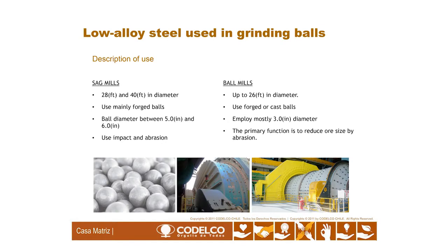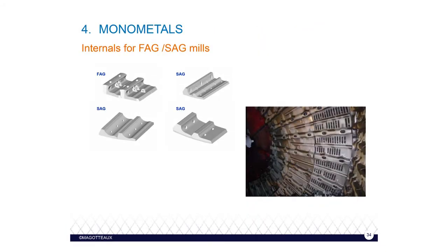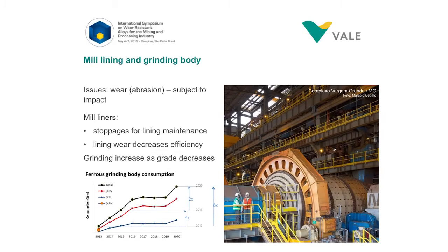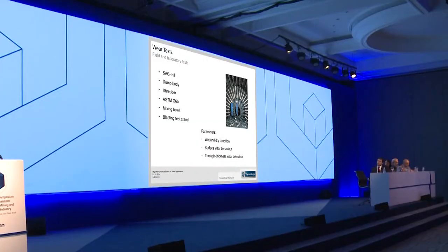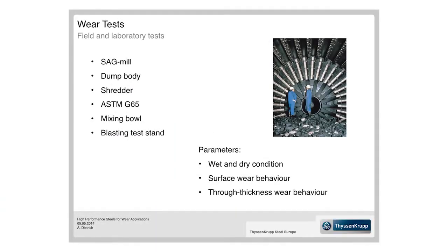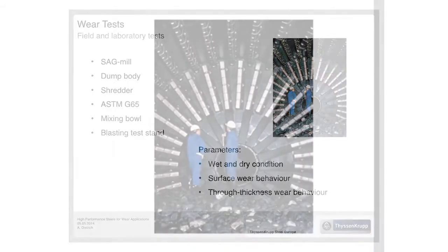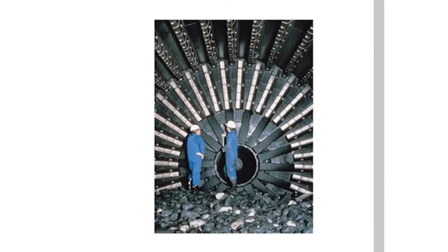Such ball mills can be internally lined with special materials, including in some cases metal matrix composites, and the various wear and deterioration mechanisms involved were described by authors who demonstrated examples of the impact of such damage on their operations. Failure analysis of ball mill liners often reveals how the repeated impact of ore particles gradually deforms the surface layers of the coating material, causing spalling and fatigue failure. Such damage has a major cost implication for operation economics and efficiency. In some instances, subsequent operations involve complex leaching operations with acidic environments, and this introduces corrosion, sometimes associated with wear, as an additional design consideration.